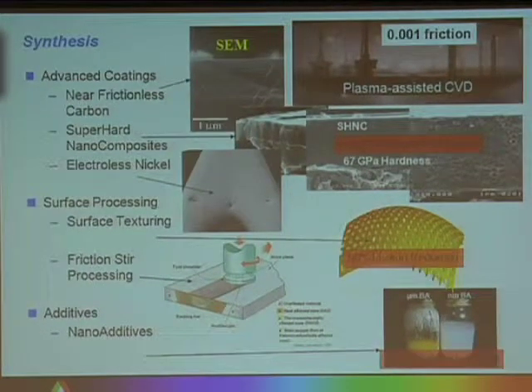In addition to the material synthesis, we are also working on various surface texturing processes. One of them is a laser micro-dimpling process that we worked on with a group in Israel. In this process, they're essentially using a laser to form very small dimples on a surface. This will influence the hydrodynamic flow properties, and you can get low friction. We're also working on a friction stir processing technique to introduce nanocomposite and nanomaterials into surface, near surface regions. And in the area of additives, the material that you find in an oil, for example, we're working on nanoparticles of boric acid to improve their performance.